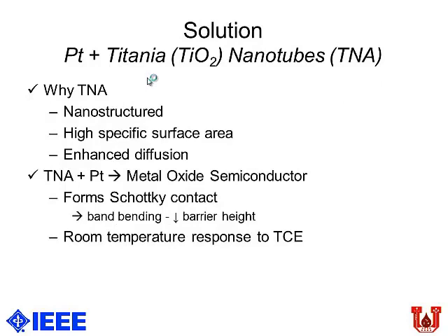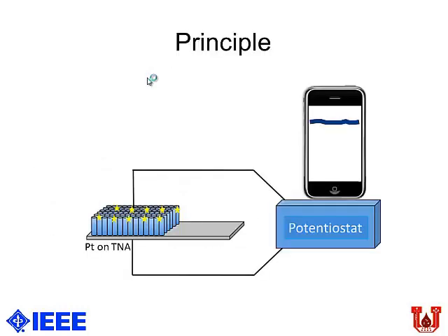It's basically using titanium nanotubes, which is nothing but titanium dioxide in the form of nanotubes on a titanium metal substrate. Titanium nanotubes are nanostructured, which means you have a very high specific surface area and increased diffusion, which is really good for detection. So we embed them with platinum, and then you have a metal oxide semiconductor, which we think is the reason the sensor gives a room temperature response to gas. So this is the basic working principle.